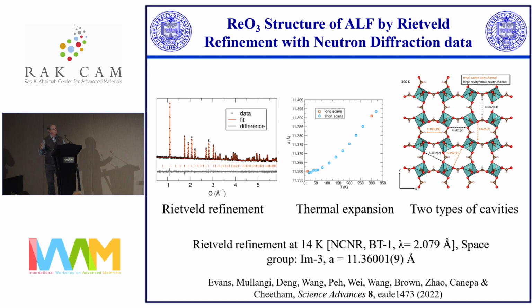completely solvent and CO2-free structure of aluminum formate, which we call ALF. So this now is a genuine MOF. It's a porous MOF. And we did the crystal structure of it by the Rietveld method. We've been doing Rietveld methods since about 1972, so we're reasonably expert at this. And we did this with my former co-worker, Hayden Evans at NIST, where they have a fabulous setup there, though their reactor's been shut down for the last couple of years. And so we're able to do the structure.